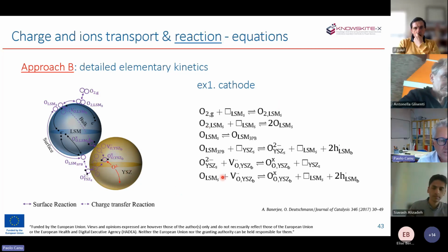So that could be a description of each single step where you see the molecular adsorption, then the splitting of the molecular oxygen adsorbed into atomic oxygen adsorbed, the surface diffusion, the reaction at the triple phase boundaries with a surface site on the ionic conductor to produce the oxygen ions within the ionic conductor, and so on. So that's a more detailed description of what's taking place within a single